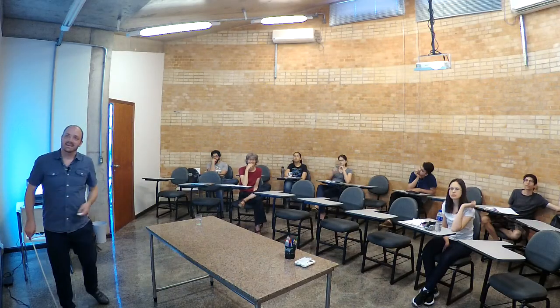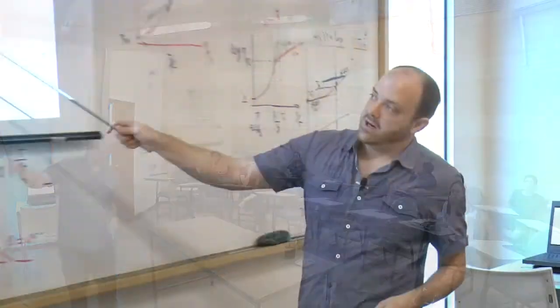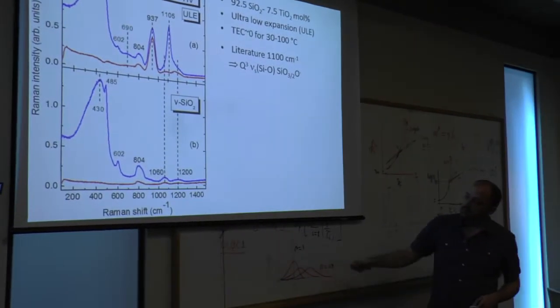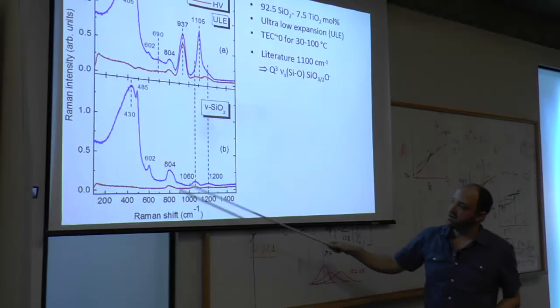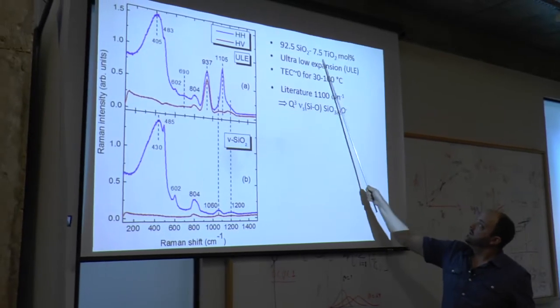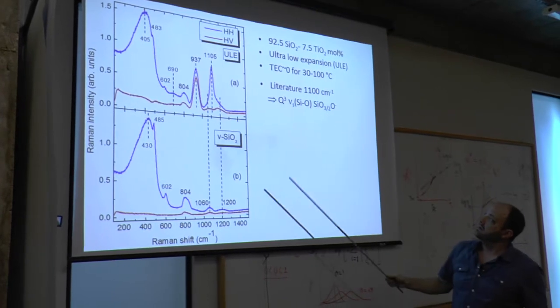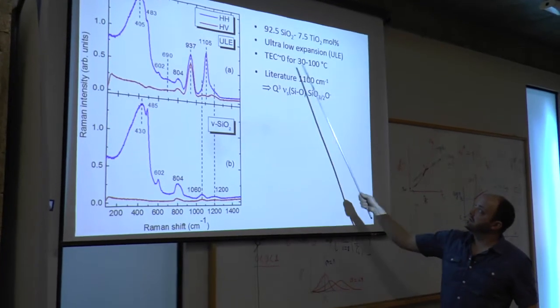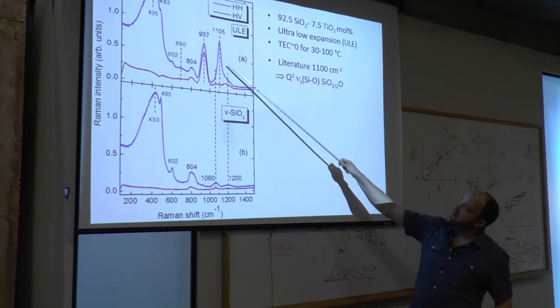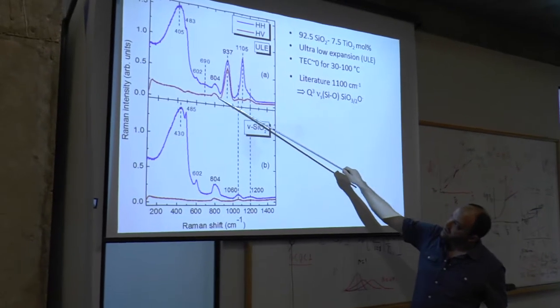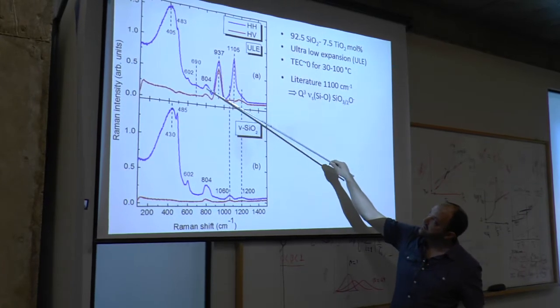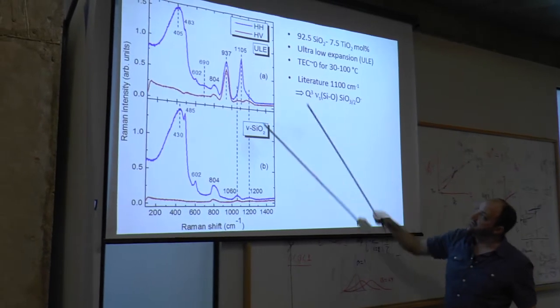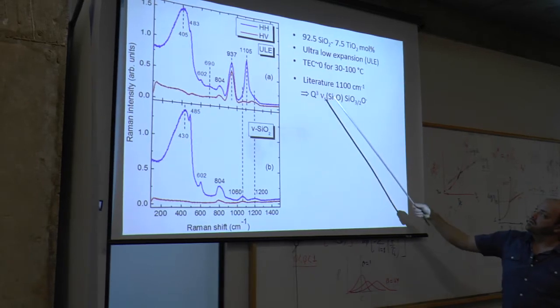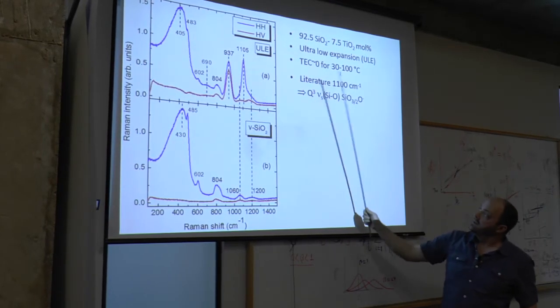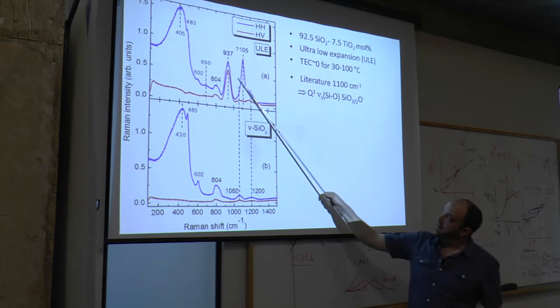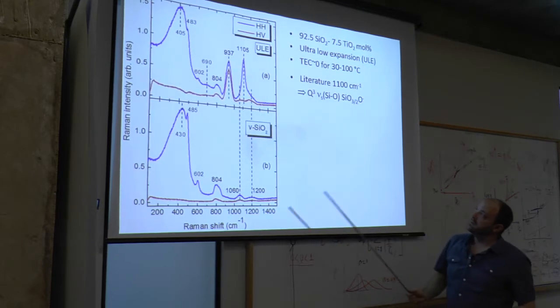Nice. So what do we see? Here on the bottom is our vitreous silica, as we saw before. We have these Q4 vibrations here. When you add a little bit of titanium, 7.5 mole %, you get this ultra low thermal expansion glass. And you see that as soon as you add the titanium, you get much more intense features around 937 and around 1100. So this 1100 band is probably related to this Q3 species, and this 937 is probably related to the titanium.